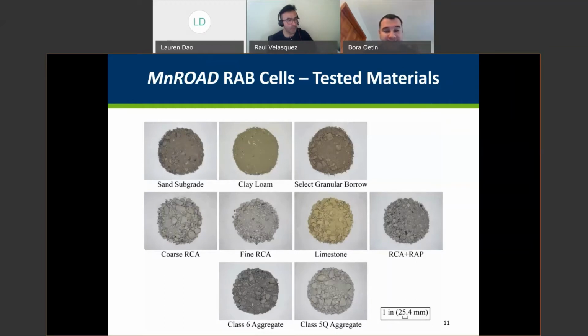And here is the limestone, as you can see, a very fresh crushed aggregate from the quarry. Class 6 aggregates and Class 5Q aggregates are basically a mix of RCA and RAP materials. As you can see from the figure on the bottom left, the Class 6 aggregate is very dark, and you can see even the black dot particles there. There are basically RAP materials. And Class 6 aggregate actually had even more RAP material than the RCA RAP mixtures, based on one of the RAP binder content measurements.